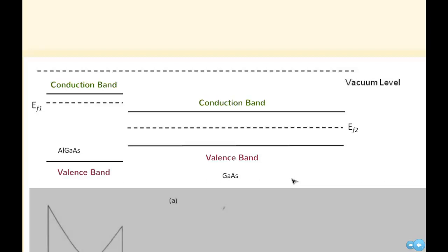Modulation doping offers an important advantage in device engineering because it provides a mechanism by which the free carrier concentration within a semiconductor layer can be increased significantly, but without the introduction of dopant impurities. Conventional doping techniques can, of course, significantly increase the free carrier concentration and conductivity of the semiconductor also, but they come at the expense of an increased ionized impurity scattering and a concomitant reduction in the carrier mobility and speed of the device. By ionized impurity scattering, we mean the collisions and scattering by electrically charged impurities and crystal imperfections.